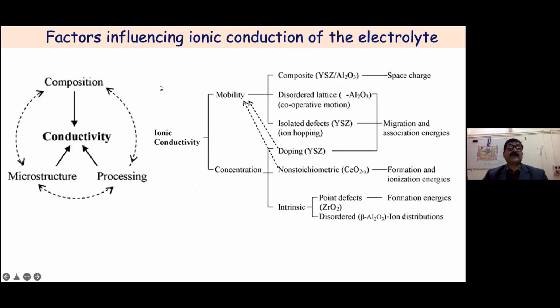You see the factors which are affecting the ionic conductivity of electrolytes: you can change microstructure, you can change processing technique, you can change composition just to affect the conductivity. Ionic conductivity depends on mobility as well as the concentration of the charge carrier, and that you can control by composition, microstructure, and processing. So this is what the different types of composition are: composite materials, disordered lattice, isolated defects in yttria stabilized zirconia, doping in yttria stabilized zirconia. They are just to change the mobility.